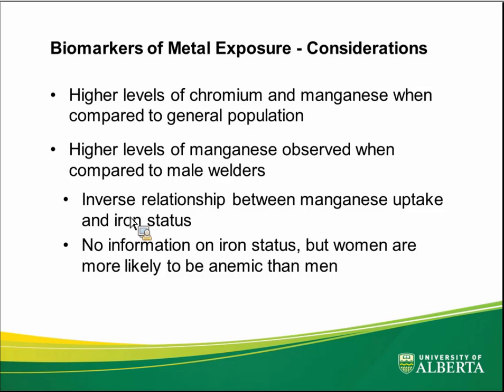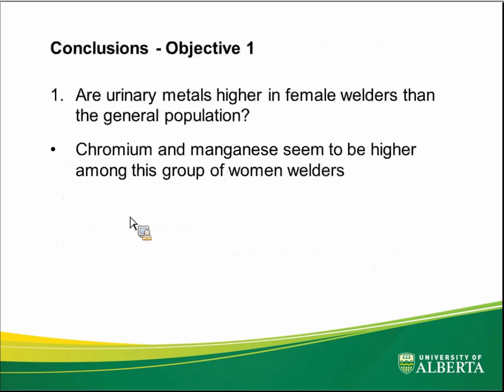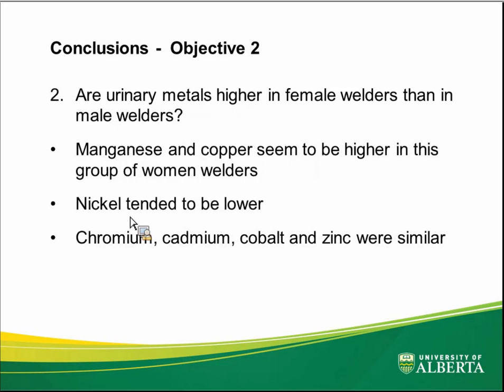So some of the considerations that came out of this: we see higher levels of chromium and manganese when we compare to the general population females. Higher levels of manganese continue to be observed when we compare to male welders. What we found when we dug into this is that there's an inverse relationship between manganese uptake and iron status. And we don't have iron status on these women. That's one of the metals that wasn't measured at the lab. But we do know that women are more likely to be anemic, and it's related to blood loss during menstruation. So the manganese observation really needs a bit more investigation. There's a potential biological explanation for that finding when we compare to the men. But we still saw the higher levels of manganese when we compared to the general population women, who presumably would have the same proportion of anemia.